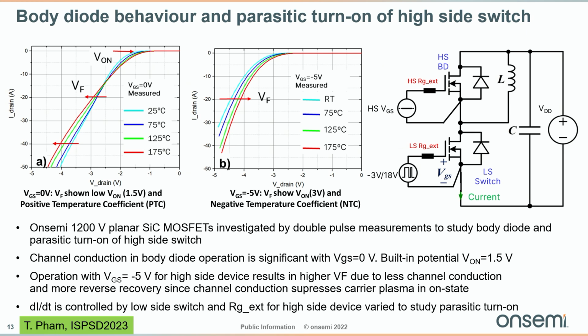Now to the body diode behavior and parasitic turn-on of the high-side switch. So for the body diode, in the left graph, you can see IV characteristics with VGS equals 0 volt. And in that graph, you can see that there is a quite low built-in potential of the body diode of about 1.5 volt where it starts conducting. And you know silicon carbide has a built-in potential of 2.8 volt or something. So this is conduction through the channel, which has a lower built-in potential than the PN junction.